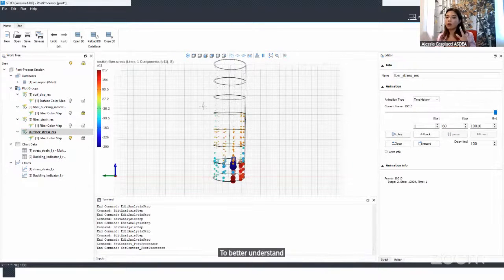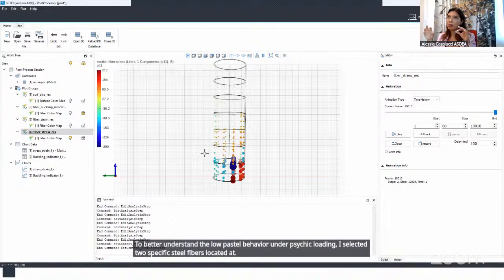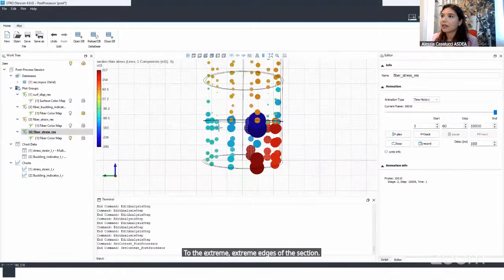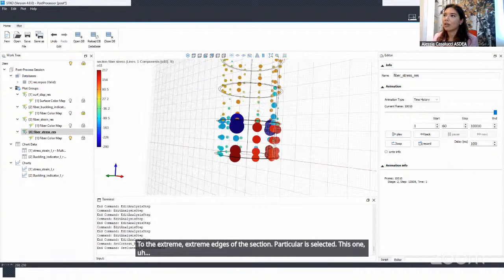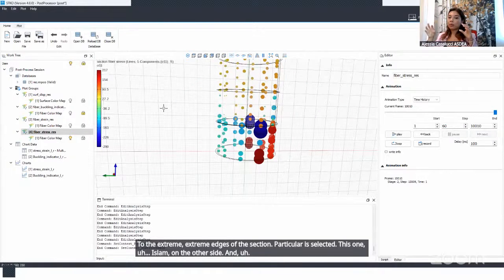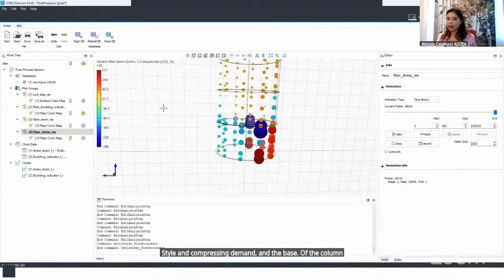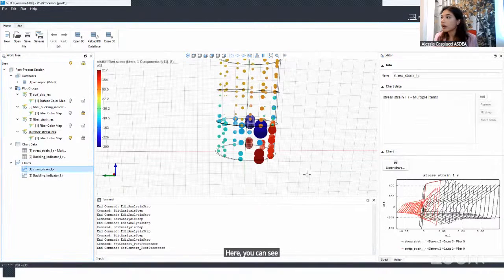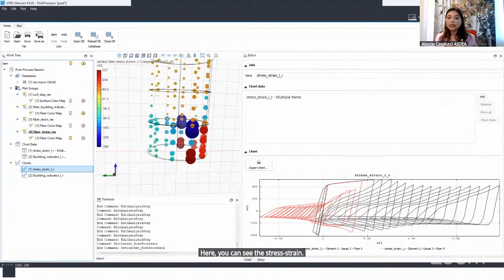To better understand the local steel behavior under cyclic loading, I selected two specific steel fibers located at the extreme edges of the section. Particularly, I selected this one and this one on the other side. These fibers are positioned symmetrically with respect to the section centroid and are representative of the maximum tensile and compressive demand at the base of the column where the plastic hinge developed. Here you can see the stress strain plot for each fiber, plotted over the entire loading history.